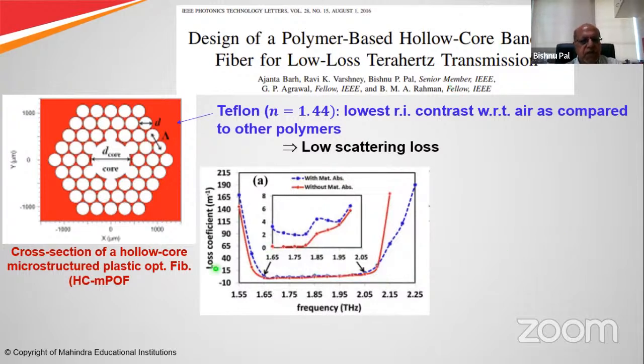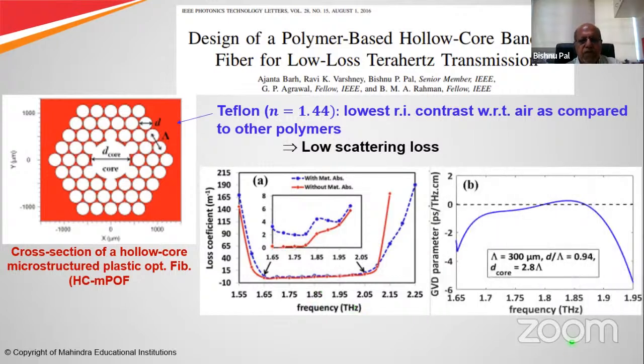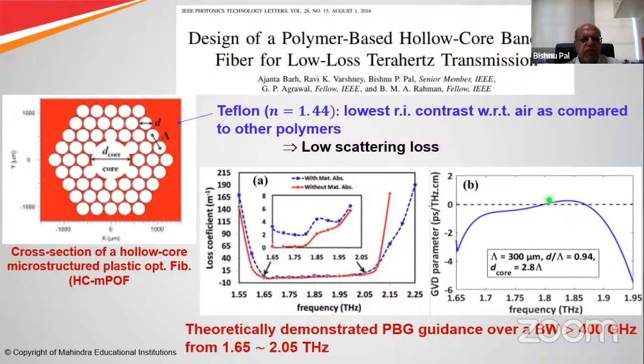This shows the transmission loss coefficient as a function of frequency in the terahertz domain. You can see the loss is pretty low, and the GVD parameter is almost flat and goes through zero again around 1.8 terahertz. These are broad characteristics of this particular fiber. We have theoretically demonstrated photonic bandgap guidance over a bandwidth of 400 gigahertz, from 1.65 to 2.05 terahertz.